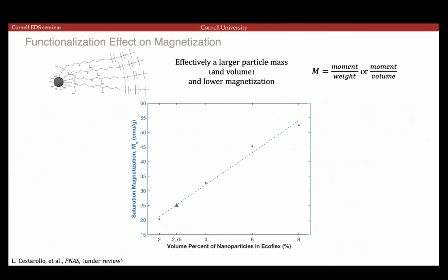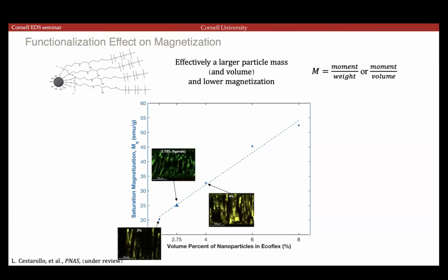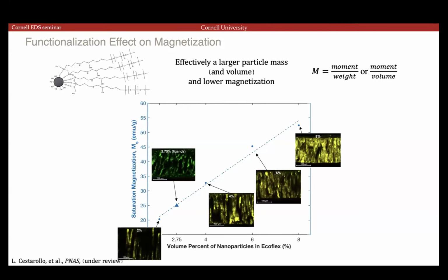And then to compare all of them together, if the magnetic moment content is the same, then the magnetization, which is the density of the magnetic moment, should also be the same and scale as a function of volume. So if we increase the volume linearly, this data point here, the triangle, is the only one that is coated with the ligands. We ended up getting a 2.75% by volume concentration. So all of them fit in a linear trend. The green one is the one that's coated with ligands.